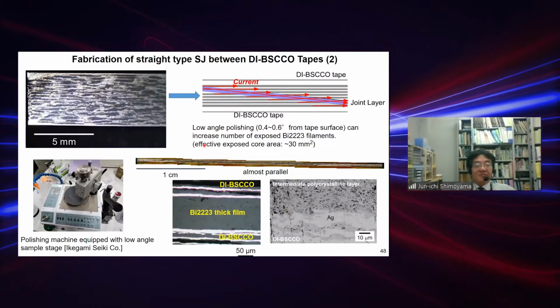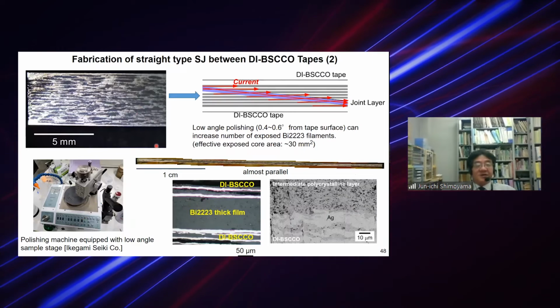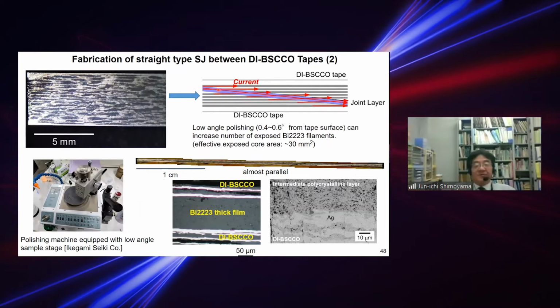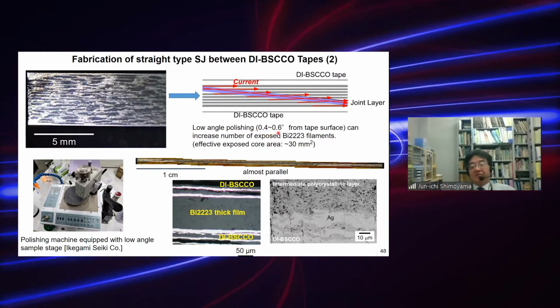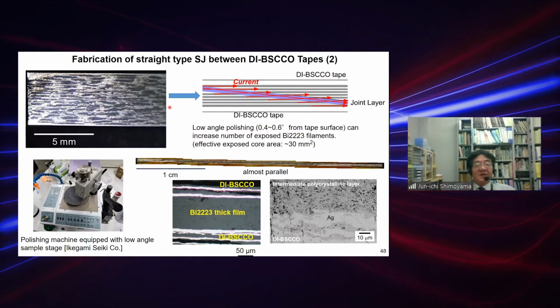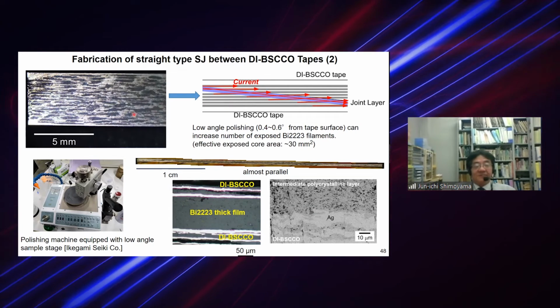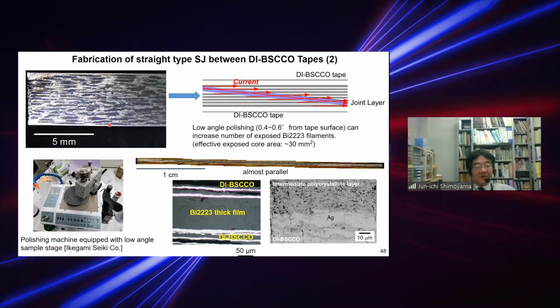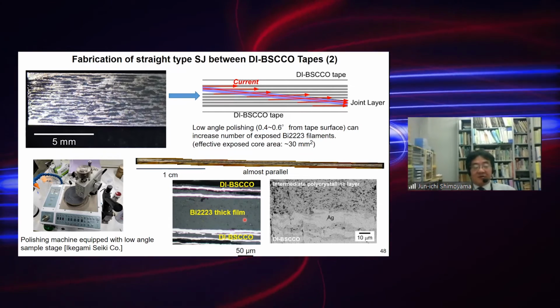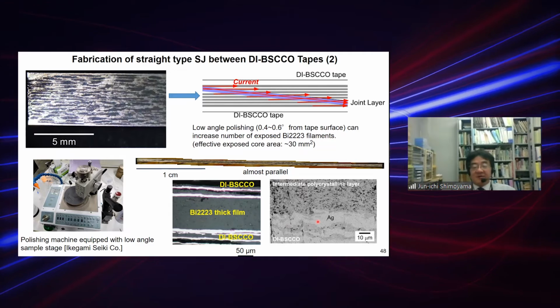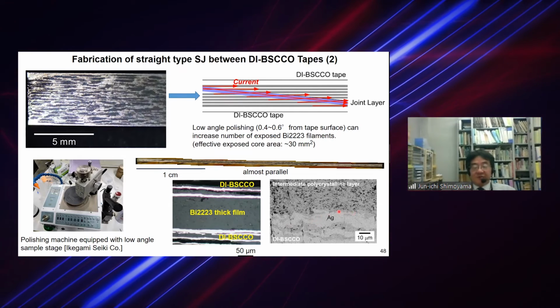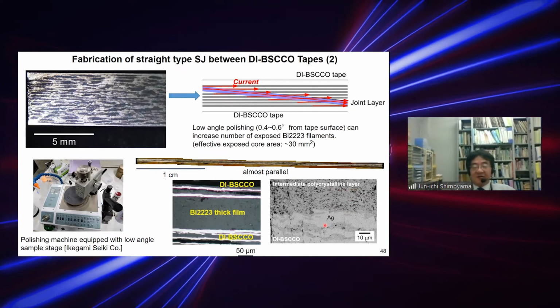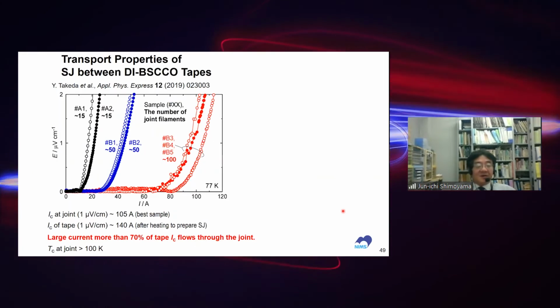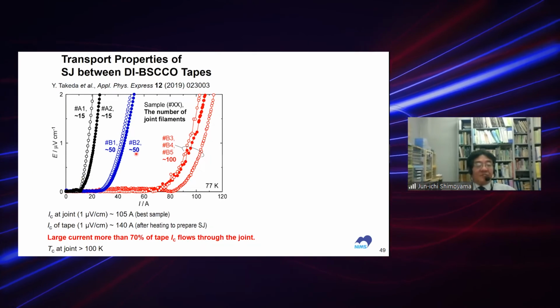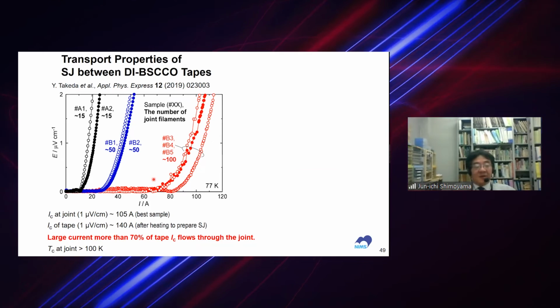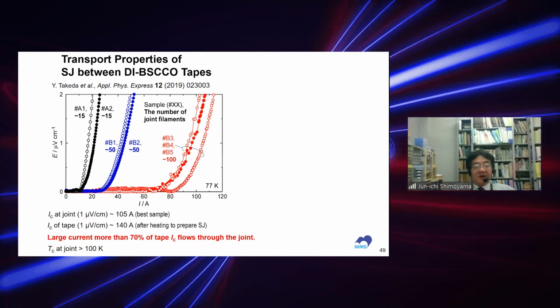The important technology is shown here. By pressing the Bi-2223 tape at a very shallow angle, 0.4 to 0.6 degrees from the tape surface, we can see many filaments after pressing. So these two tapes are connected by Bi-2223 thick films, and there is a very good connection between the polycrystalline layer and the Bi filaments. By increasing the number of filaments, joint Ic increases in this way.